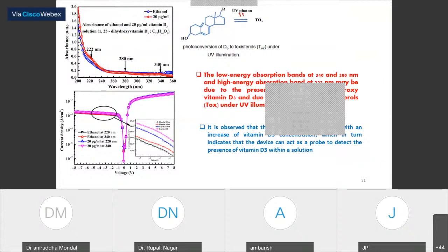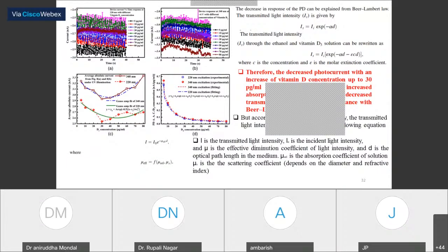of this vitamin D, which is dissolved in ethanol, and the photocurrent which has been determined for the vitamin D in the deep UV and the UV region. We have seen a clear enhancement of the current of the photodetector due to the presence of the vitamin D inside the ethanol. So we have measured several characteristics for different concentrations of vitamin D in the ethanol, and we have seen that the responsivity of the photodetector is different for different percentages of the vitamin D.